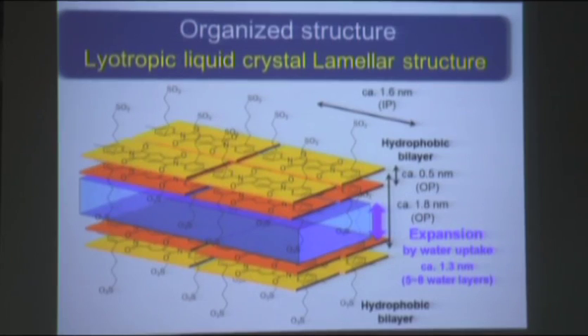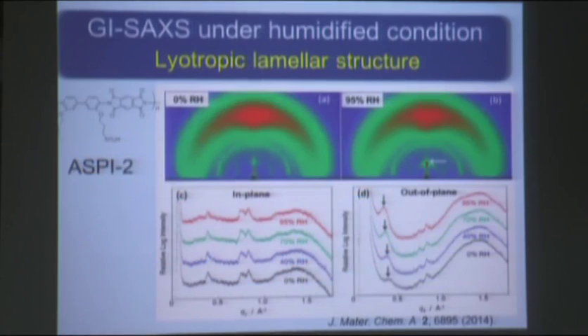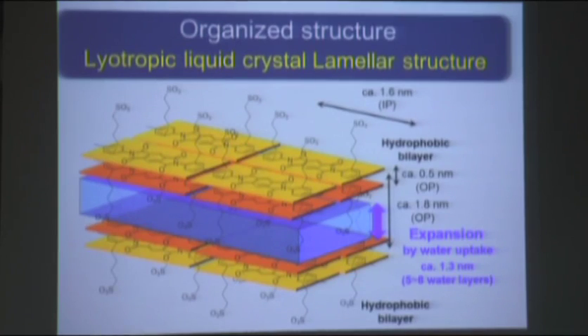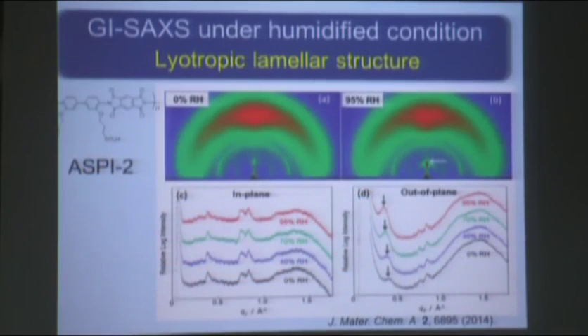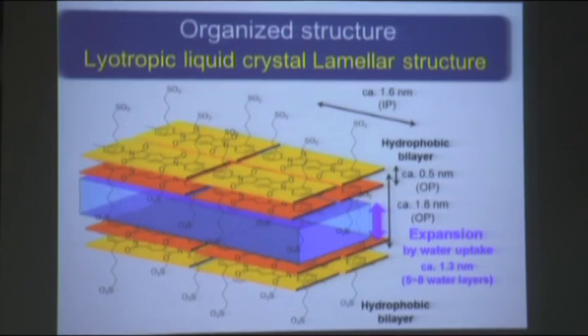So here is again shown the organized structures. You see this is in plane 1.6 nanometer. This corresponds to the unchanged peak here. This is polyimide, so please don't look at this. And this peak corresponds to this direction. This means as the humidity increases, the water comes inside of this polyimide, so that the water can be introduced here, then expand this direction. So the changing value corresponds to this expansion, so that we can see the 1.3 nanometer very thin nanochannel for proton transport.